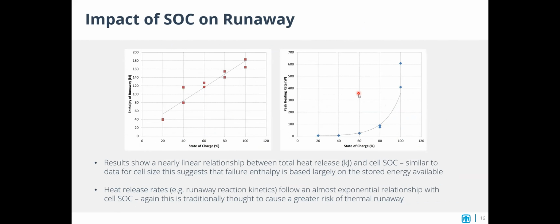Another thing that was also touched on is that state of charge is very important for total heat release and heating rates, where essentially a fully charged cell will release more heat than a discharged cell, or even a partially discharged cell. So if possible, always working with a discharged cell will release less heat than a fully charged cell.